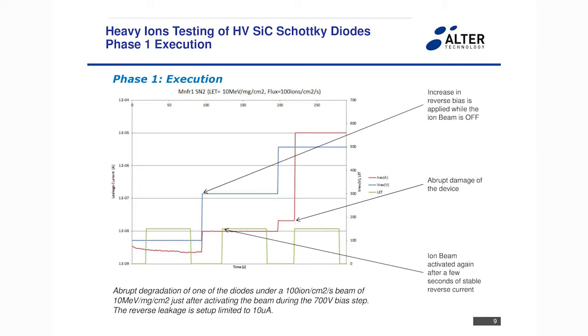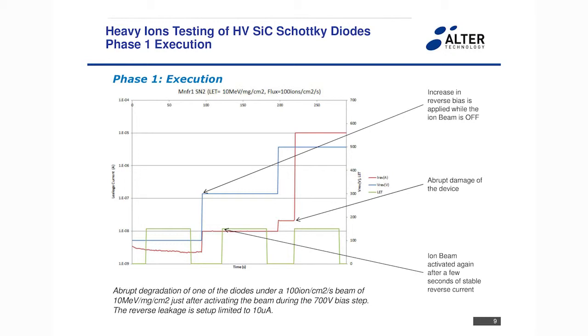Okay, this is the same graph I showed at the beginning, but a bit explained. We performed several beam steps while increasing the reverse voltage, and we plot the reverse current during all the tests. So we don't raise the reverse voltage from a step to the next one with the beam on, because otherwise, if the device is damaged, we wouldn't know if it's just the electric field or because the device was a bit damaged or something. So we wait for a few seconds and then turn on the beam. So here you have, just starting the beam, you have the damage, and this current is the setup limited current.